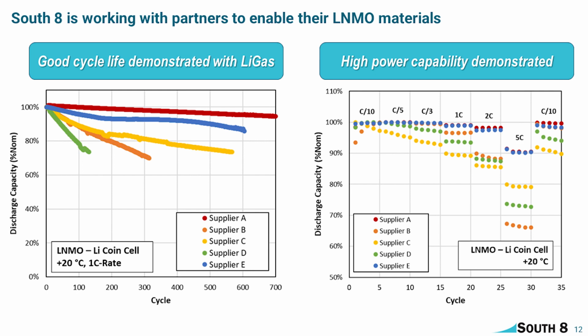And we're also doing some high power testing. So over here, as advertised, the LNMO is a spinel structure. It should show very good power. And here we're showing up to the 5C symmetric charge and discharge rate, really good capacity retention. This is an excellent material to enable fast charge needs in the automotive industry today.